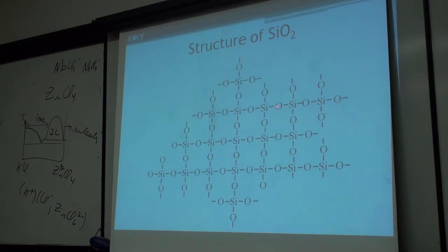If you make this angle less, then the energy goes way up, because the 2 oxygens are coming next to each other, and the electron clouds come next to each other. So you can't change the angles. These are tetrahedral angles, and you can't start changing them without greatly increasing the energy. So the thing tends to be a very rigid structure. It's highly viscous, about 20 orders of magnitude more viscous than calcium oxide, for example. It's way more viscous than, say, honey. This is really viscous stuff.